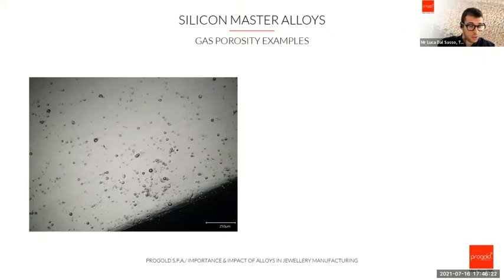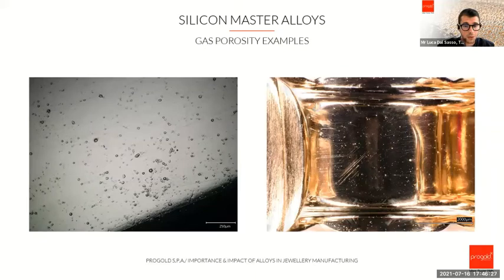Going on with another very known example of defect, we have the gas porosity example. As you can see, on the right side you have the original piece, and on the left you have the microscopic picture of these small holes. These small holes are the bubbles that form during the solidification of the metal. So once the metal starts its solidification phase, the gases that are inside the metal are not able to stay inside anymore. And so once they try and go out, they form this kind of round bubble.